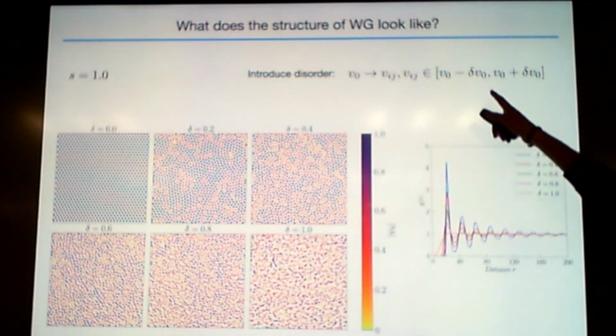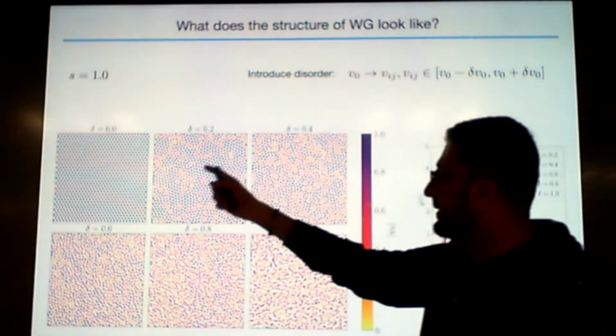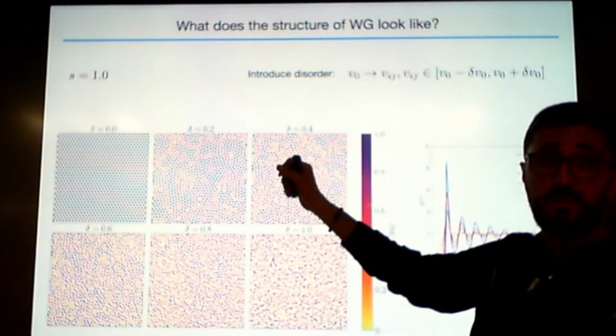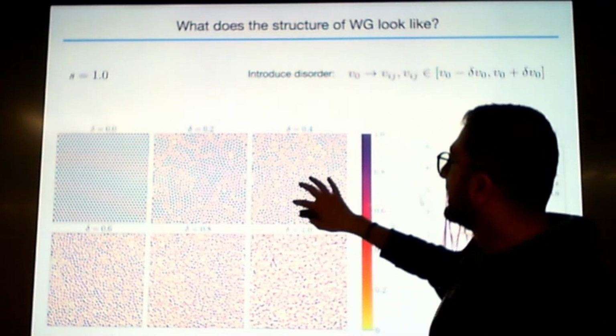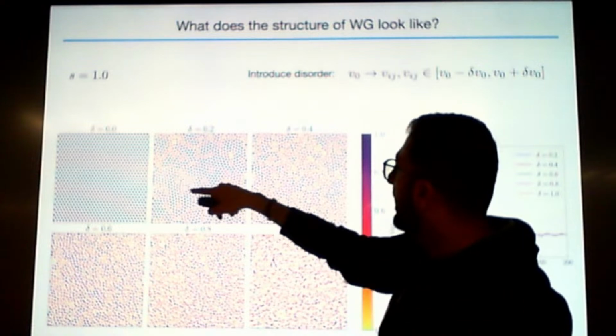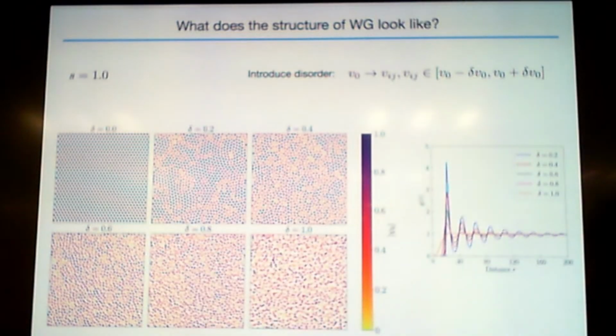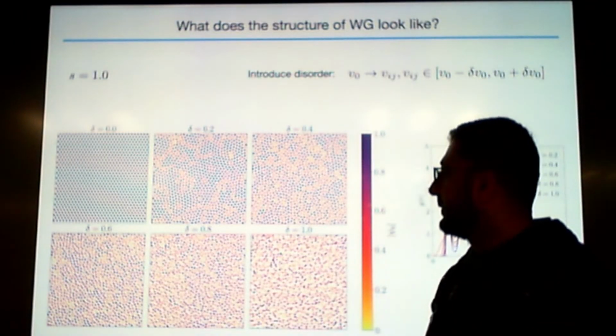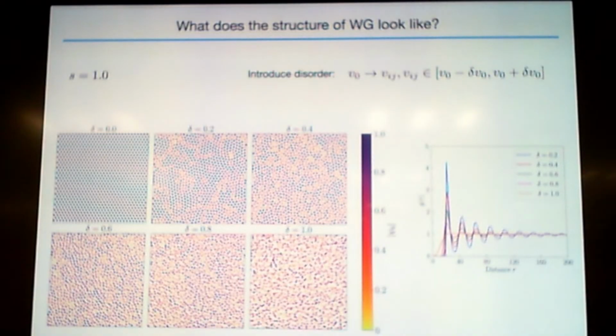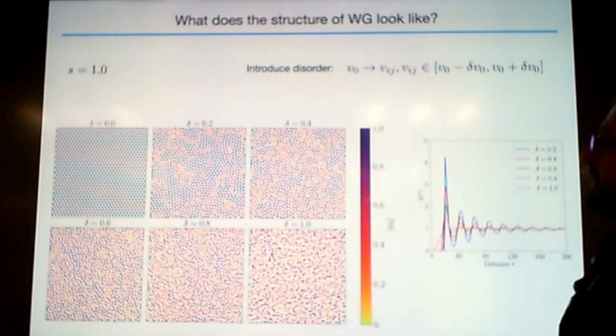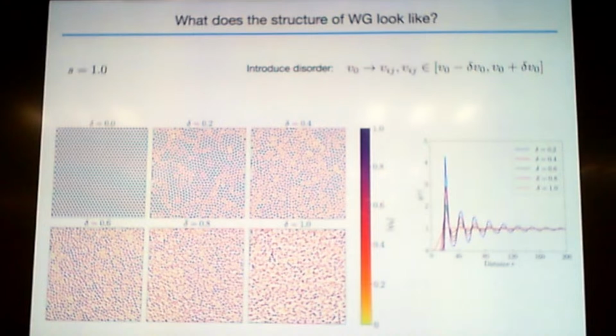So come back to delta, to the width of the distribution. If the distribution is 0, you end up in a crystal, obviously. If your distribution is still small, you still have crystals, I would say, with some grain boundaries, and you keep losing this. And you get the highest disorder in some sense for the largest delta you have, which is 1, by construction. Now, it depends a lot on how you anneal the system, because at some point you don't equilibrate anymore. You have to wait very long to equilibrate. And when you're below the Tg, you would have to wait infinitely long to equilibrate, but it doesn't happen, obviously. So these technical details depend on annealing rate, etc.